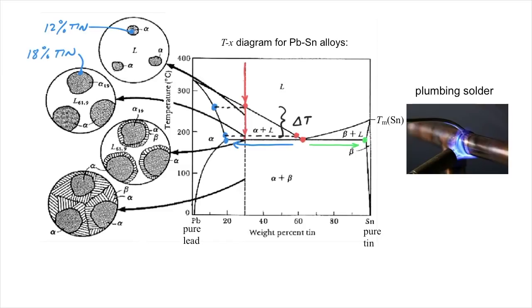What this example illustrates is that even though the microstructure of solder is not an equilibrium structure, thermodynamics nonetheless has an important impact on many aspects of this microstructure. These include the composition inside the lead-rich and tin-rich layers, the presence or absence of the lead particles, and the gradients in composition within these various regions, all of which have important effects on the homogeneity, structure, and properties of the solder.